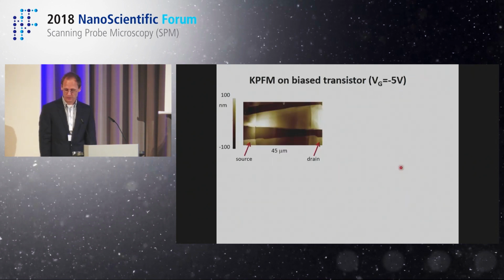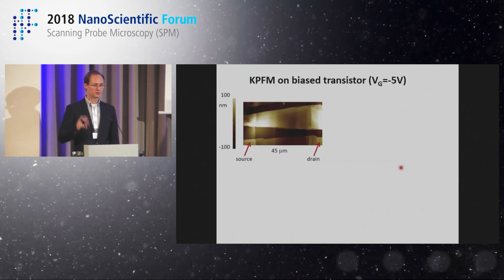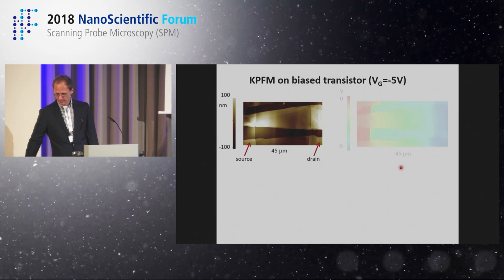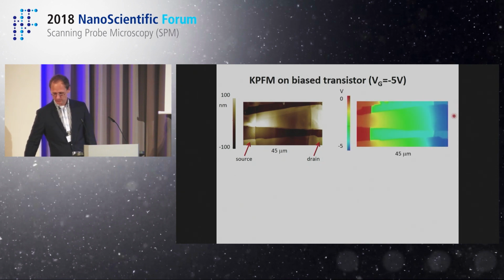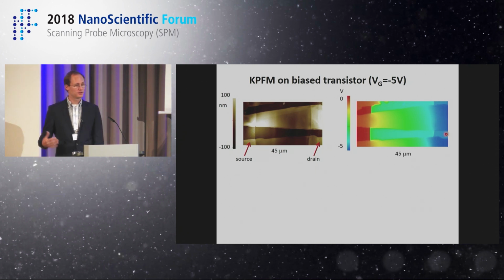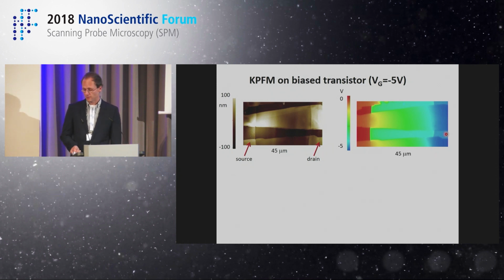So in a transistor, we go even a little bit further, and we do not look at the system all connected to ground, but we look at a system where a current is flowing across our microchannel, and we can do the same experiment. Now, what we observe here, so that's the whole microcrystal bridging source and drain electrodes, and here is the KPFM map. What you can see here is that our electrodes are no longer connected only to ground, but just the source electrode is at 0, and the drain electrode, you see, is biased externally at -5 volts.